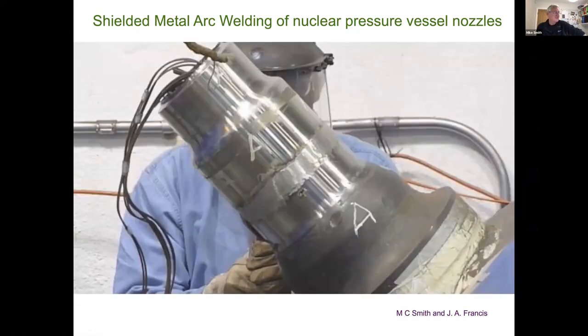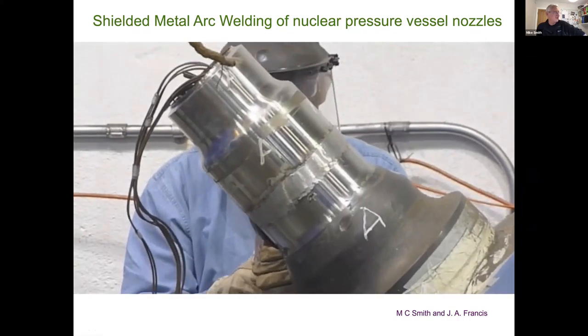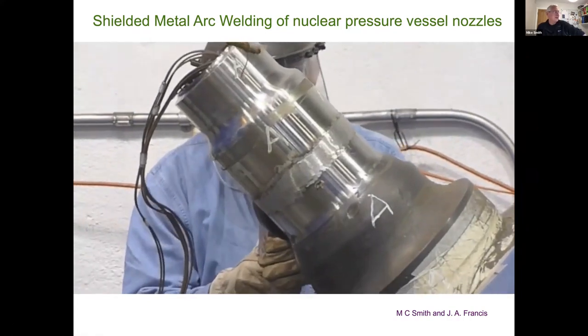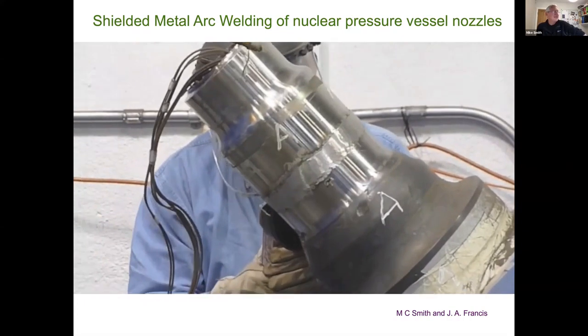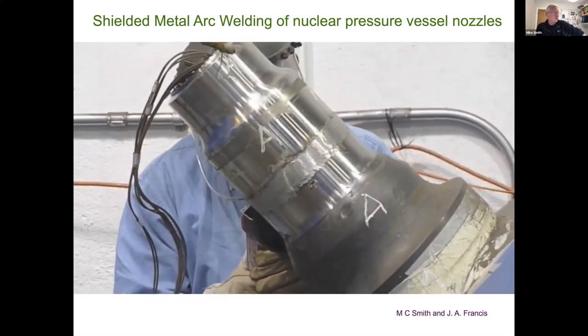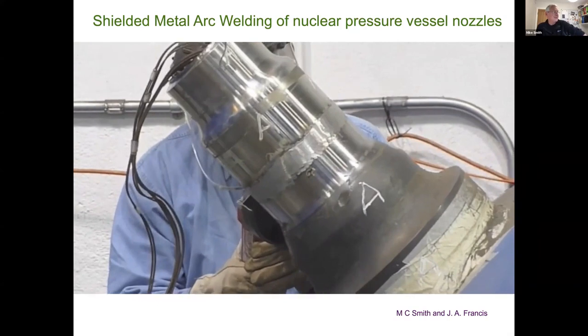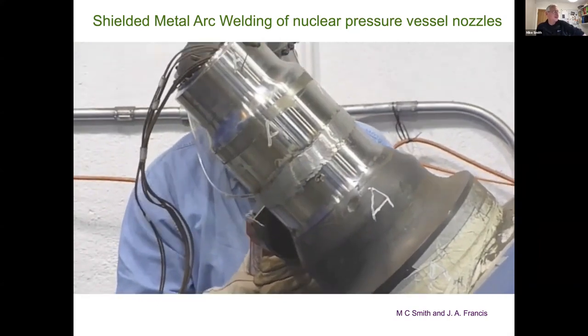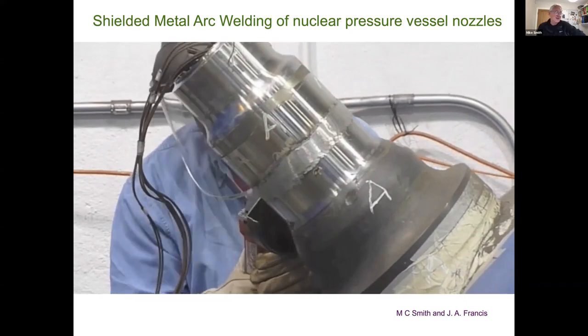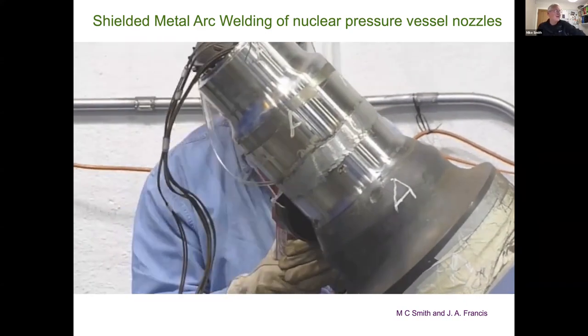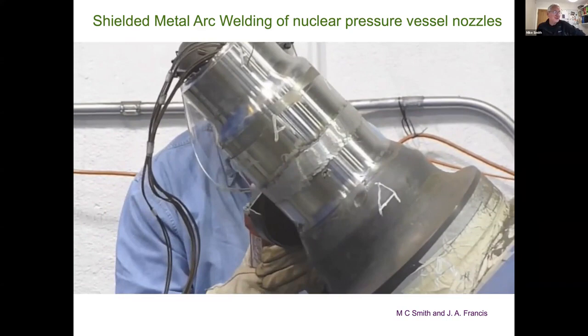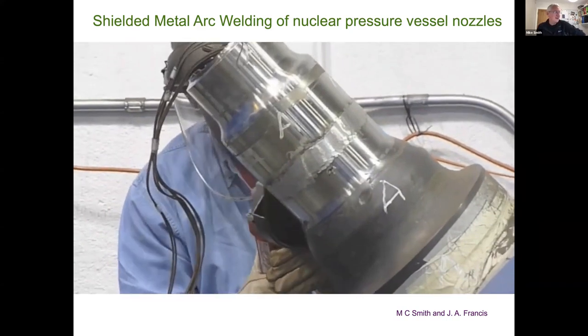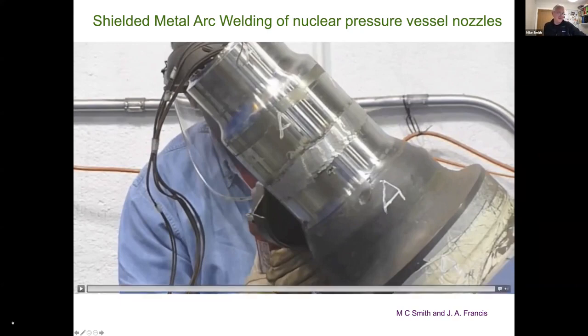One of the things you then do at the end, if you remember me talking about crevice corrosion in a bolted joint, once you've completed a weld like this, you usually grind off the top surface of the weld, what we call the weld cap or the weld crown, because that's got quite a rough surface. So it's potentially a site for preferential attack due to crevice corrosion. It also makes it difficult to perform inspection on the weld, because you can't do ultrasonics through a rough surface very easily. So that's something we'll come back to in lecture 4.